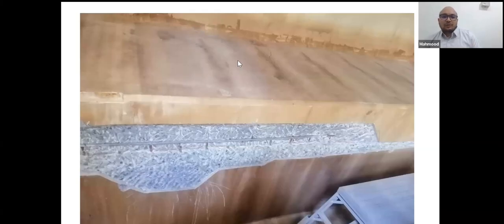This is how the contamination will be. Epoxy coating is still there, but this is a plant where there's a lot of seawater contamination. It's a cooling area, a cooling tower. You can see how the color has changed, and for repairing, they will make the socket. They will remove the loose particles. Then, as we saw previously, they will apply the epoxy bonding agent. They will use a polymer modified cementitious mortar. And also there is an epoxy mortar, based on the site condition and the client's requirement.